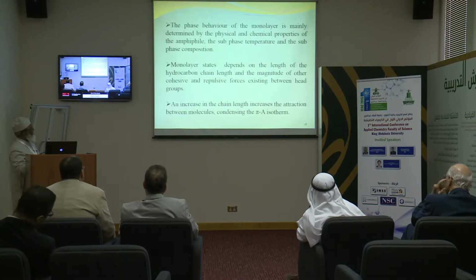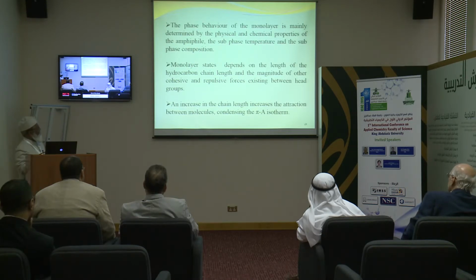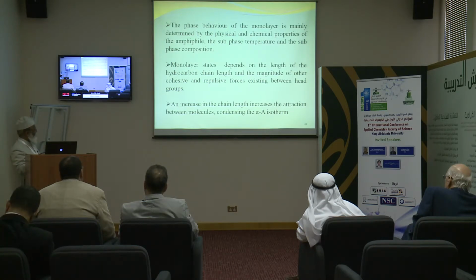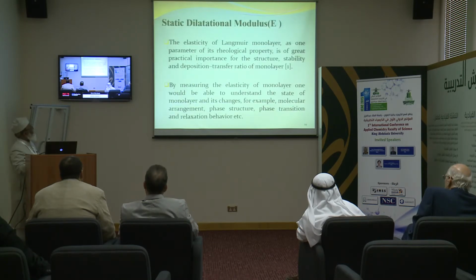The phase behavior of the monolayer is mainly determined by the physical and chemical properties of the amphiphile, the sub phase temperature and the sub phase composition. Monolayer states depend on the length of the hydrocarbon chain and the magnitude of the cohesive and repulsive forces existing between head groups. An increase in the chain length increases the interaction between molecules, condensing the surface pressure area isotherm.